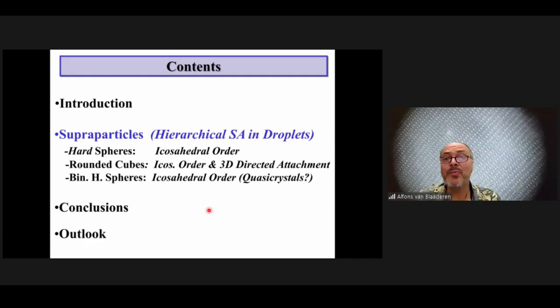That's just one example of why we want to structure on multiple length scales. But now let's go to some of the fundamentals, what was a real surprise to us, namely that if we do the self-assembly of particles of which we know the interactions quite well, then for superparticles built up from on the order of 100,000 nanoparticles, we found different structures as compared to the structures in the bulk.